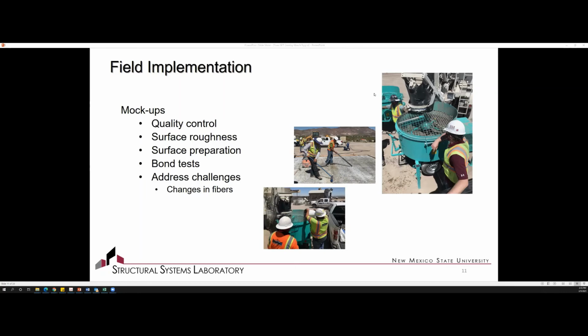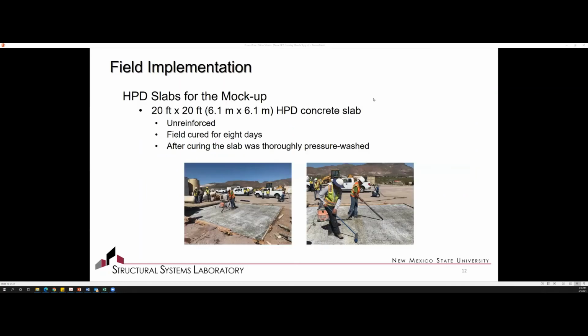So initially we were working with the contractors on one mock-up slab, and these slabs were 20 feet by 20 feet. With this, the concrete that was going to be used, the HPD concrete slab, the deck that was going to be placed, was unreinforced, and these were field cured for a minimum of 7 days prior to putting the overlay on the mock-up. After curing, the slabs were thoroughly pressure washed and cleaned just to ensure that we have a good surface for bonding. Within these slabs, we also did a couple of different things.